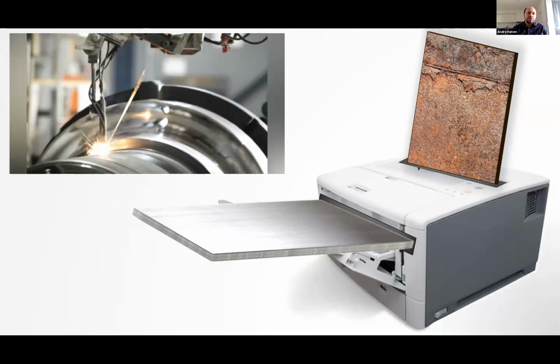The better behavior was attributed to a higher passive film stability, which is a common protection mechanism found in stainless steels. But why was this protection enhanced in the printed materials? Our further investigations revealed that the distinct microstructure produced by LMD favored a more stable passive film on the surface of all stainless steel types. Our results, therefore, confirmed that we can actually print stainless steels with better corrosion performance than traditional materials.